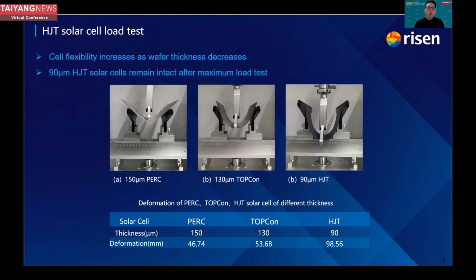The other aspect, which Christian also mentioned: in common sense, people may think that with the thinning of the wafer, it will be more fragile compared to the conventional one. But by testing, we compared the 150 micrometer PERC cells, 130 micrometer TOPCon cells and 90 micrometer heterojunction cells. The PERC cell cracked when the deformation reached 46 millimeters, and the TOPCon cracked at 53. But the heterojunction, even when reaching the maximum load test, still remained intact, which verifies the reliability of thinner, ultra-thin wafers for heterojunction.